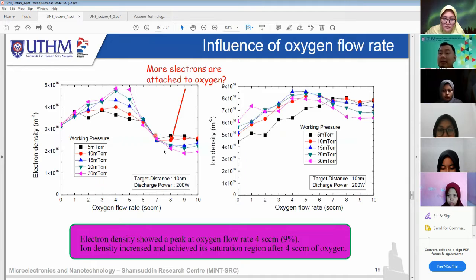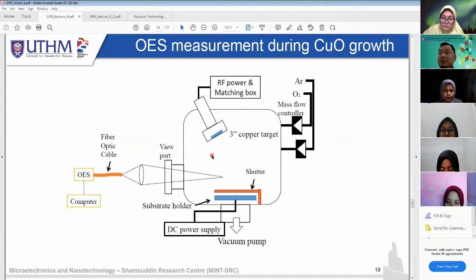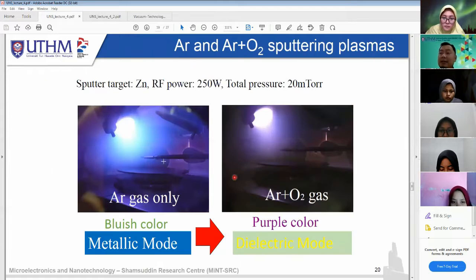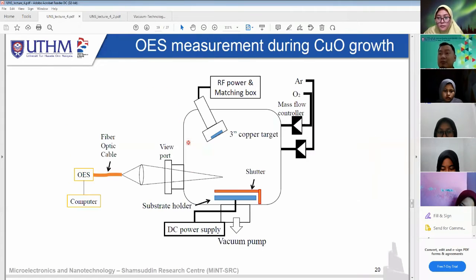So this is how we can study it. I think this one I did discuss last week, where we use the Langmuir probe analysis to capture the electron density and the ion density here. So just an overview about it. And then we have this OES measurement to capture the emission from the plasma. Because we can see here, the color is different, right? When the color is different, it means that we can capture some information from this. So we use the optical emission spectroscopy technique to capture this.